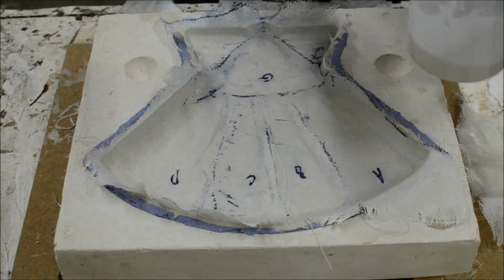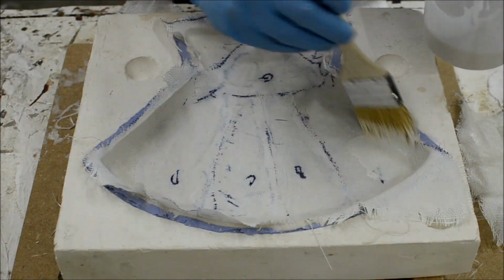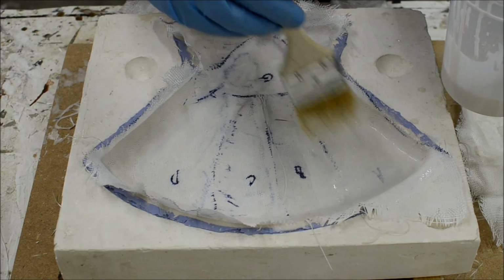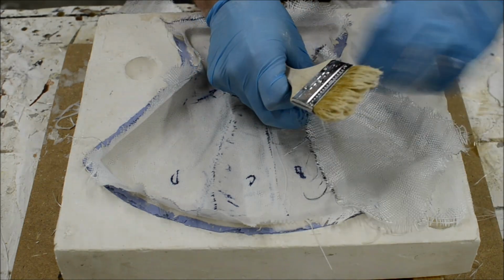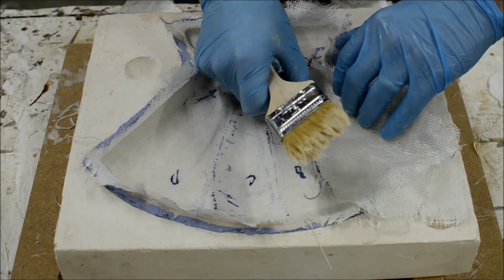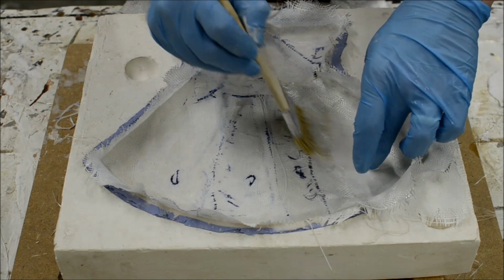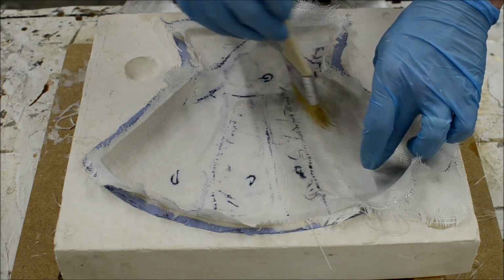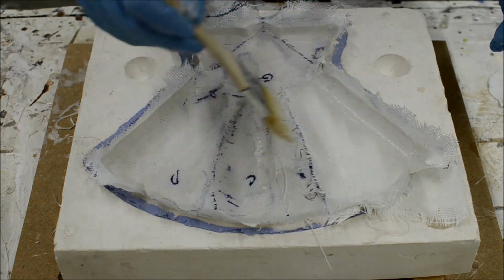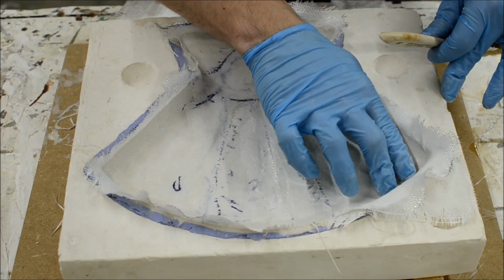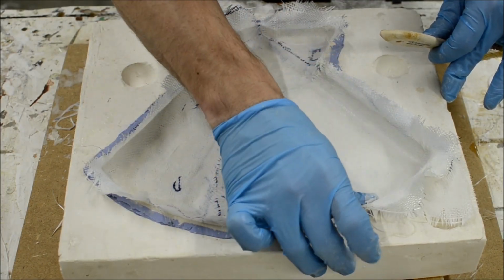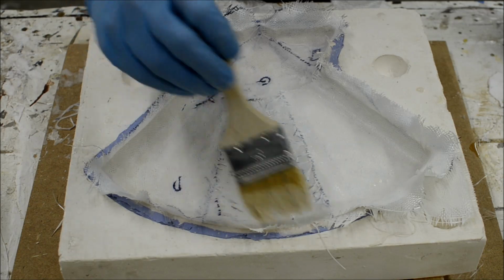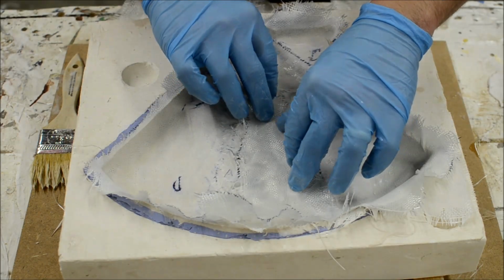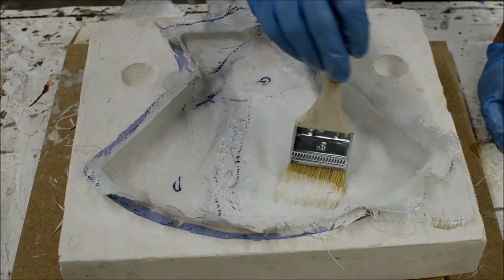Once you have one layer of the mold completely covered, begin covering with a second layer in the same manner, but crisscross the strips over the seams of the previous layer so that the strands are running in a perpendicular direction. Do not pick up or slide the fiberglass cloth once it has been placed down in the resin. Again, work air bubbles out by pressing or rolling. All the pieces need to be pressed fully against the layer before it.